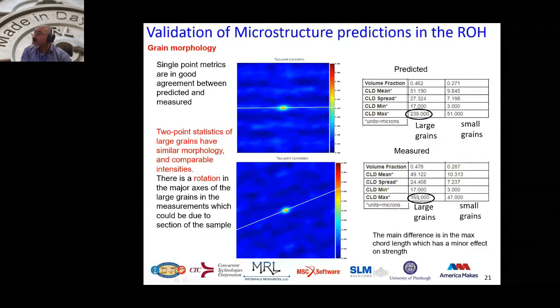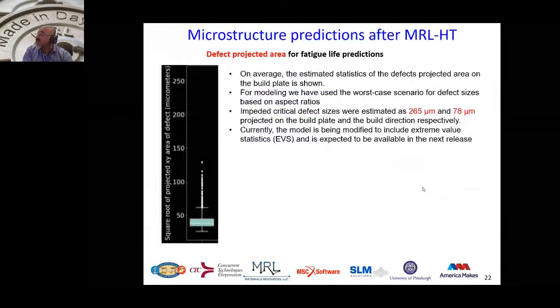For the dimensions of the grains, we were close enough, but this is part of the extreme measurements, and our prediction is slightly different than the measurements. But when you are looking at mean behavior, you rarely take into account the maximum. So our mean is pretty close, 51 and 49, and our spread is pretty close between them. The maximum is something that we can use later on with extreme value statistics to define it.